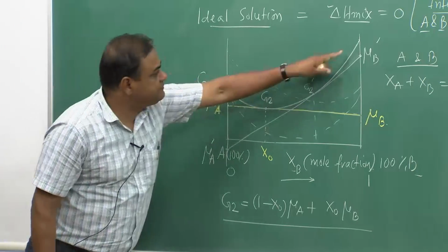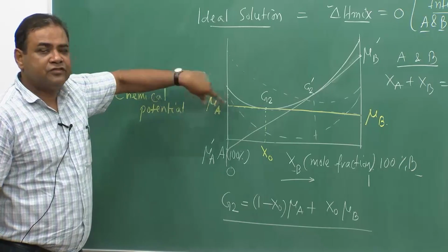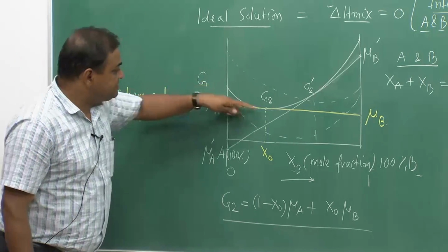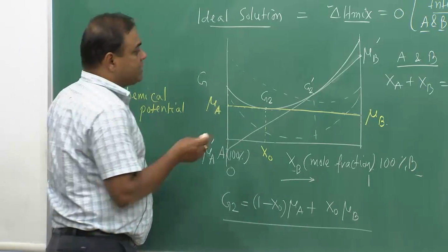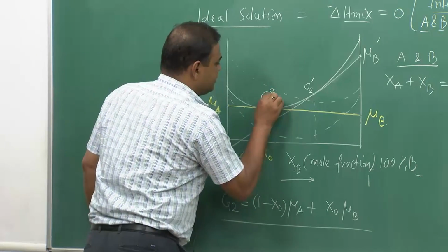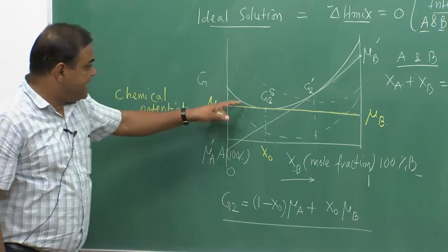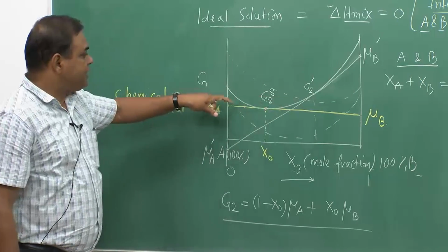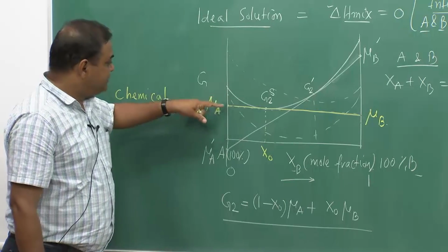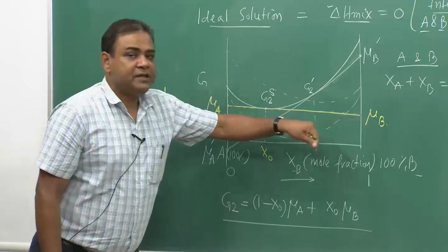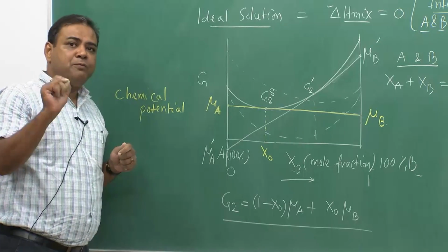And whenever we have this graph, since we are considering a complete solid solution, it is a graph for a particular phase. And let us say we consider that it is a graph for solid. Okay. Now, that means at any point, if we try to draw a tangent over this graph, then these intersection points will be the mu values, the chemical potential of that particular component